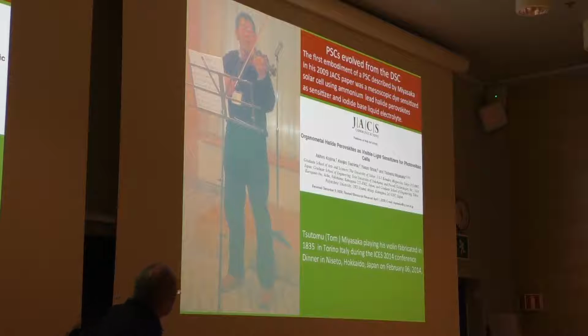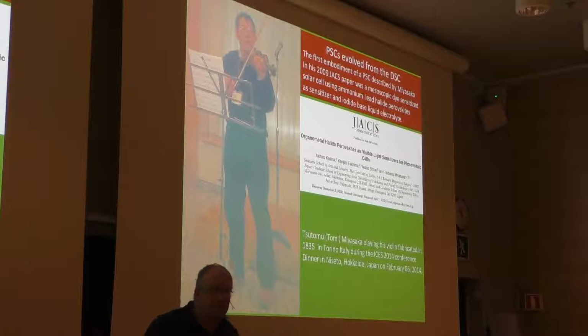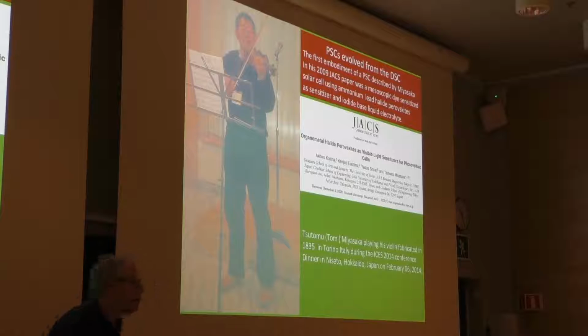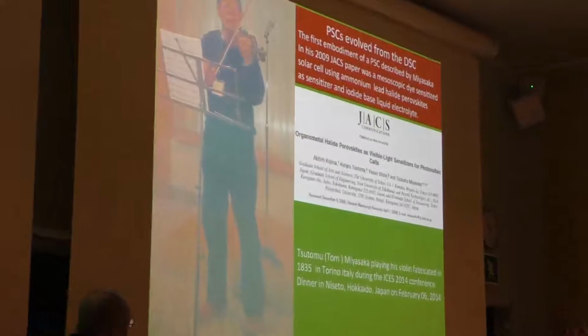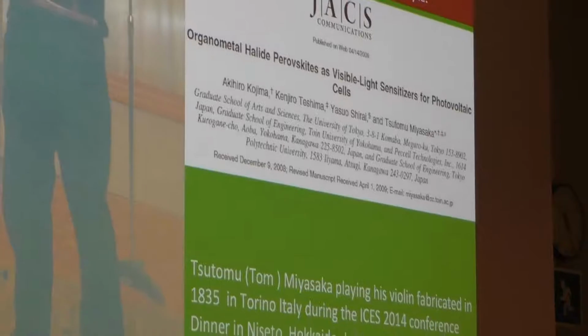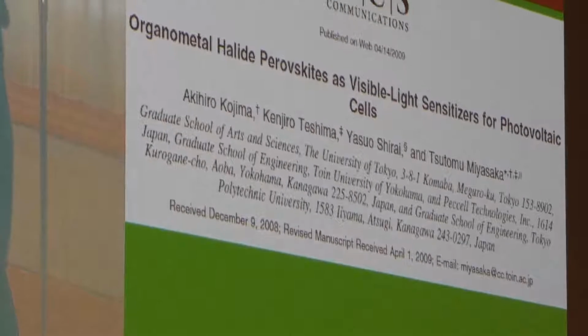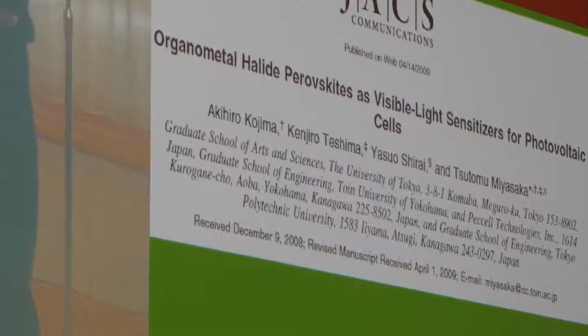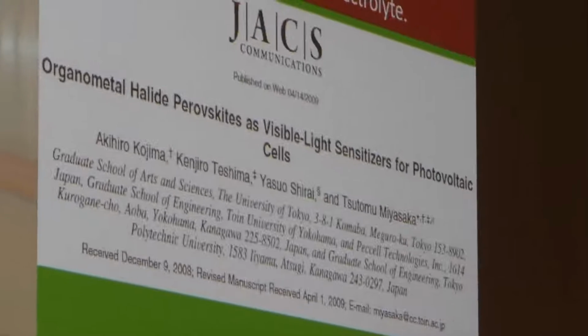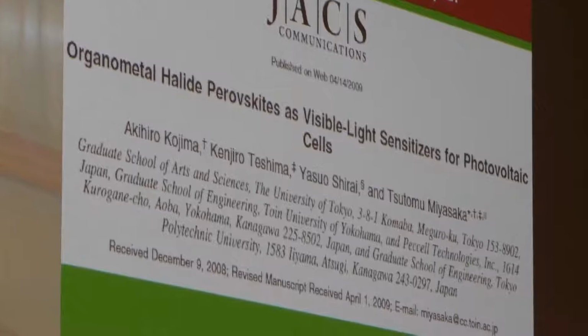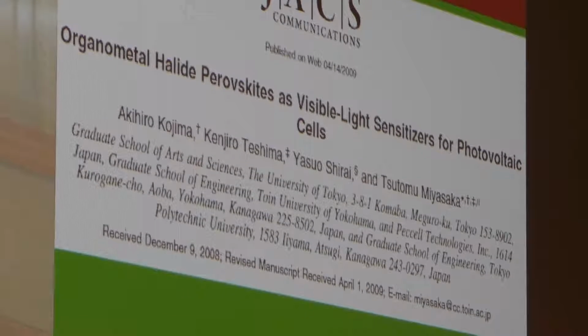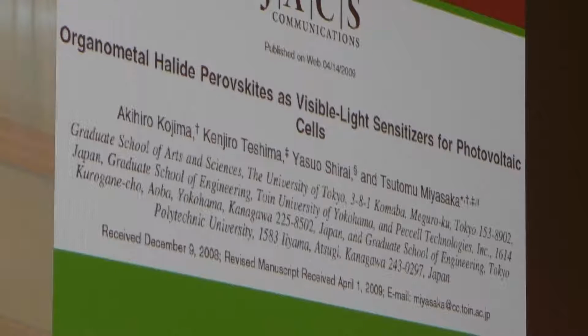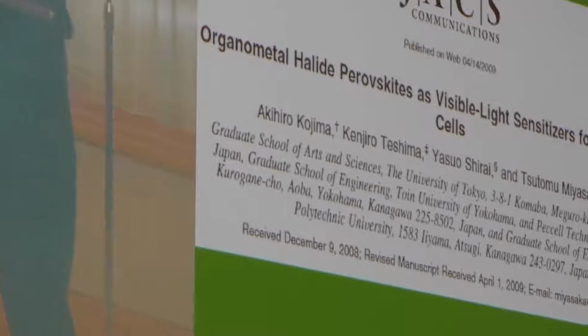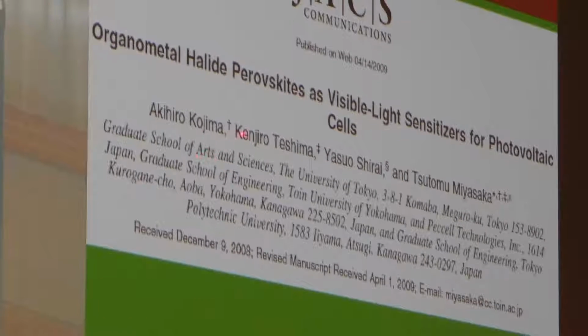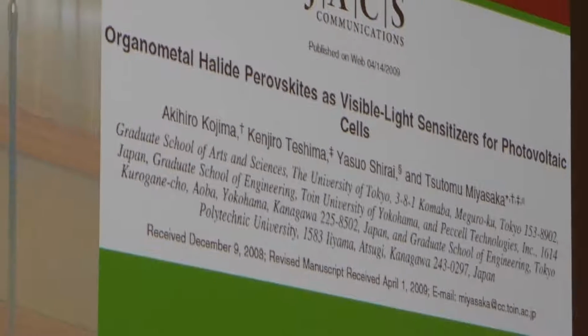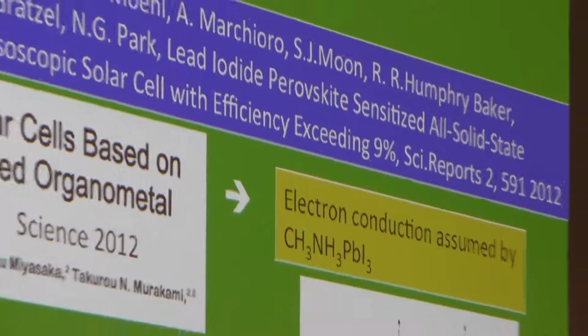Another hobby he started in the early 2000s was to try to use perovskite material as a light absorber in a quantum dot solar cell. He started, as far as I know, to talk about it in 2006. He said that I have this perovskite, I have 2-3% efficiency, but I have to be very fast to measure it with the iodide electrolyte, because it's stable for maximum 10 minutes. So I really run into the solar simulator, do the test, and then it corrodes. So he published this in 2009,